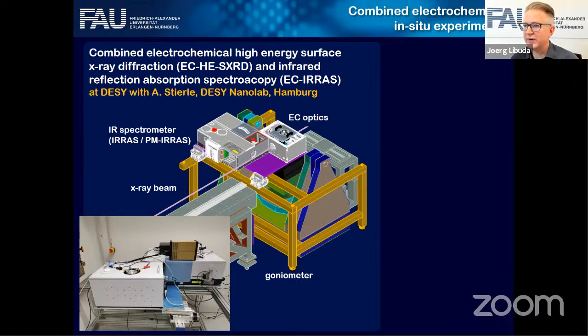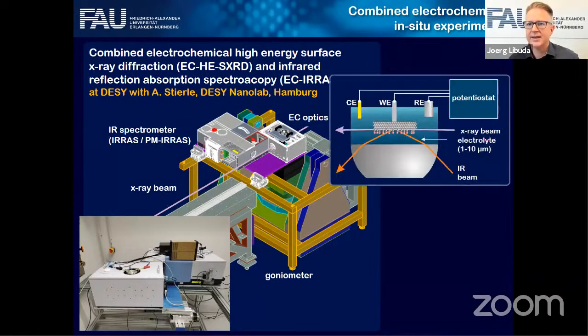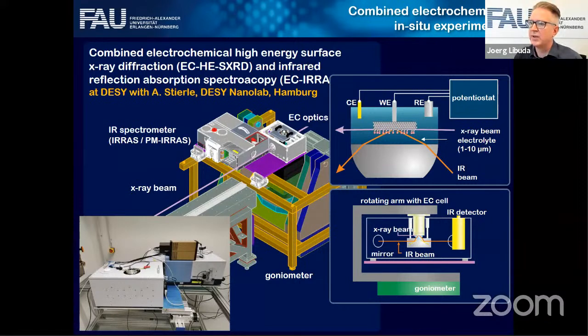Surface X-ray diffraction, as mentioned, is also a very powerful technique. So at the moment, we're trying to bring these two techniques together in a new setup. That's a combined X-ray diffraction and infrared reflection absorption spectroscopy system that we're currently setting up at DESY NanoLab, together with Andreas Stierle from DESY. And the idea here is to do these two experiments at the same time in an electrochemical environment. So you have your model system here. You come in with your X-ray beam and do a surface X-ray diffraction experiment. And then at the same time, you do your infrared experiment. Of course, it's not so easy because you have to think about all the alignment and so on, but we think it's possible. It's in the process of being set up. And the potential is, I think, huge, because you can learn about the structure and the chemistry at the interface at the same time.